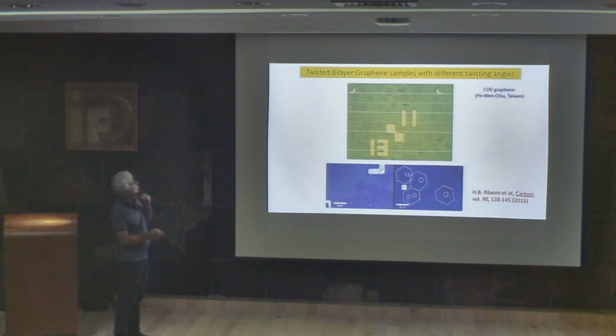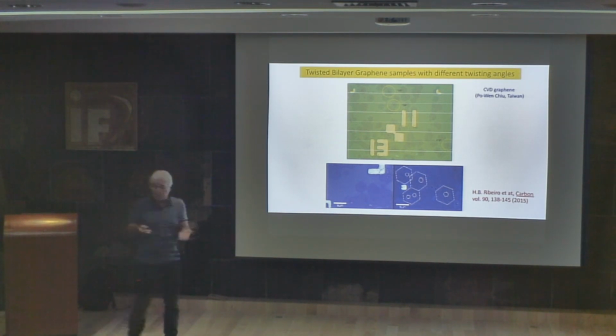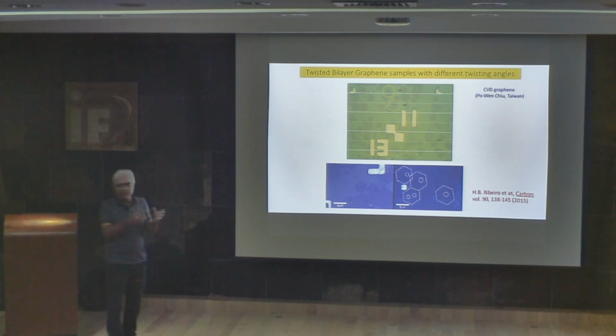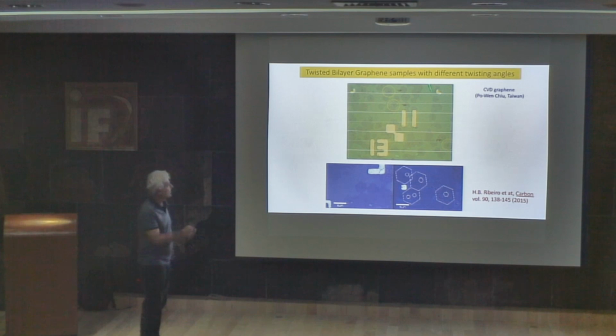Okay, now I will show some results in samples of twisted bilayer graphene. Laura is making very nice samples of graphene here. And by changing the parameters of the system, you can also synthesize this kind of sample. This was done in China. But you can see many hexagons, and the light part is one layer, and in the center we have a second layer. Then we have twisted bilayer graphene.